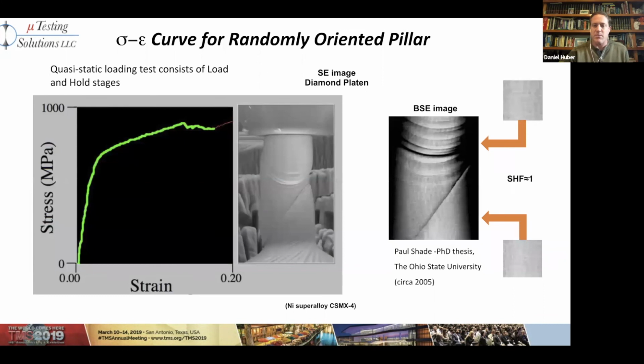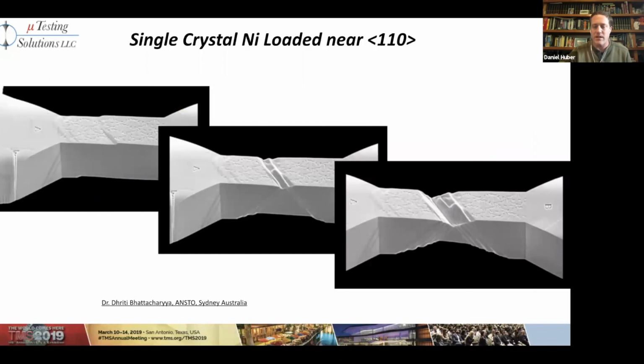So here's an example of a microcompression pillar that's been tested and uniaxially loaded. This is Paul's work back in 2005. And then over here, this is a micro tensile specimen. The grips have actually pulled the material. You can see the formation of the shear bands and whatnot. So really interesting if you want to go study these different arcs. Now you've got the strain, you know, the loading, it's all confined. You can actually go back and create a TEM foil directly from the specimen and get a look inside.